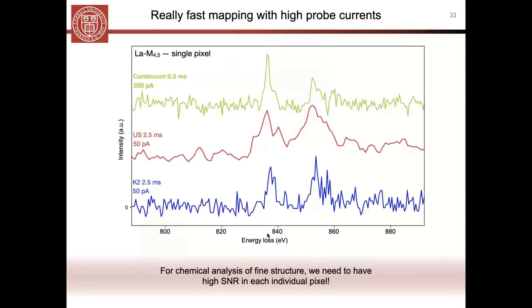And so, the last thing to mention is I keep going on about how we want to do chemical information. And so, of course, for that, what you need to have is not just a nice looking map, but also a nice looking spectrum, a nice looking single spectrum, right? Again, once you sum over 10,000 or 2,000 spectra, everything starts to look pretty nice. But the real test is when you look at a single pixel, single spectrum, can you still tell what's going on in your EELS edge?